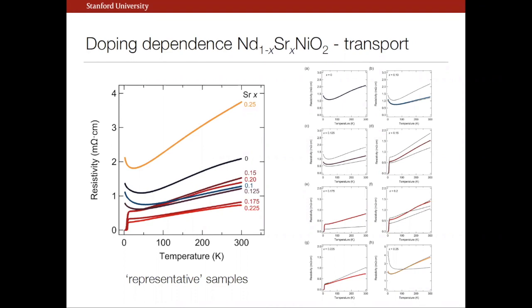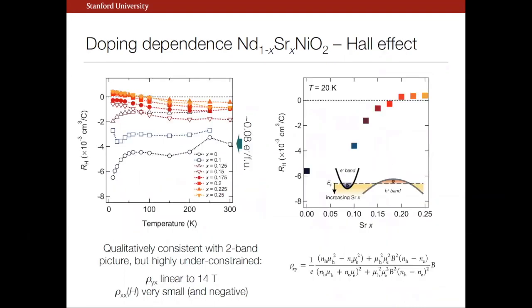Okay, so this one's been done in the literature before, but 3 samples for each of these, and the colored one is the one we use here. So hopefully, some of them you can't see, there's a second one too. We just took a middle typical one. Qualitatively, the temperature dependence is reasonably close to one another, and it's again as if we have a series resistance that you have to consider in terms of these defects. If you look at the Hall coefficient as a function of this doping series, it varies quite smoothly. I'm almost done with it.